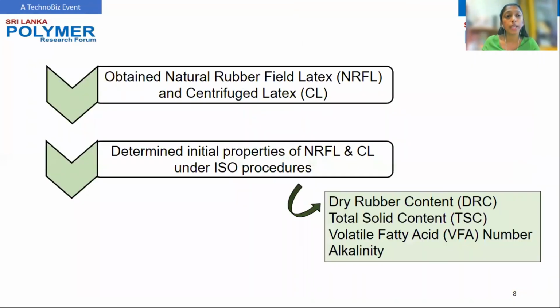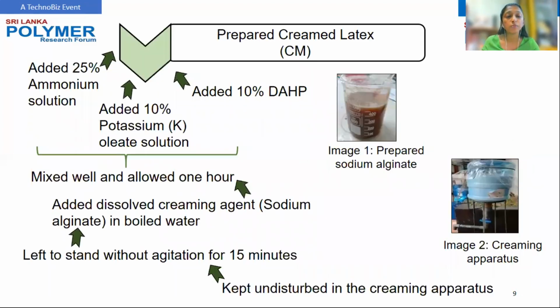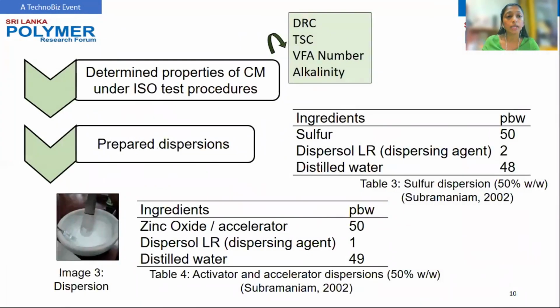First, the initial latex properties of the obtained natural rubber field latex and centrifuge latex were determined according to the ISO test procedures. Then, cream latex was prepared from the obtained natural rubber field latex, and the cream latex properties were determined under ISO test procedures. All water-insoluble ingredients were generally added into latex as dispersions. So, 50% sulfur, accelerators and activator dispersions were prepared separately.